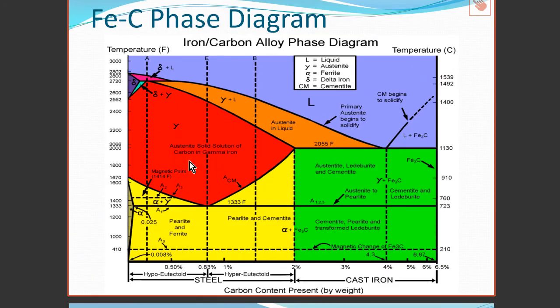We have austenite, which lives in this region. Okay, red hot iron, single phase. Red hot steel will be in a single austenite phase. And when you cool it down, it's going to want to split up into cementite and alpha iron. When it does that, it forms a microconstituent, a eutectoid.